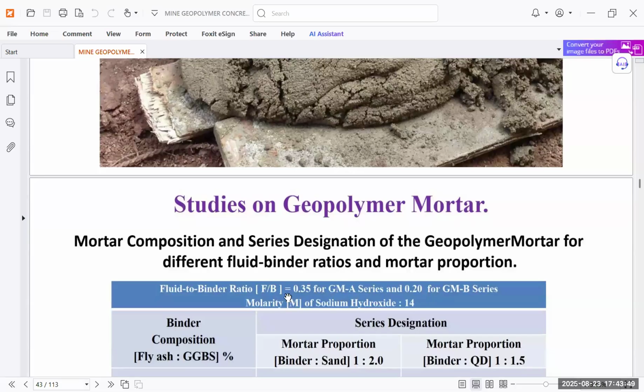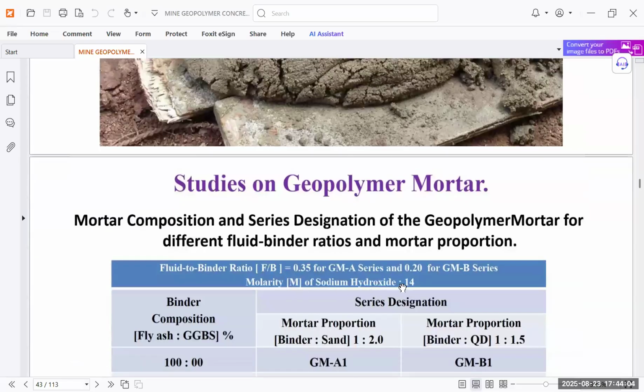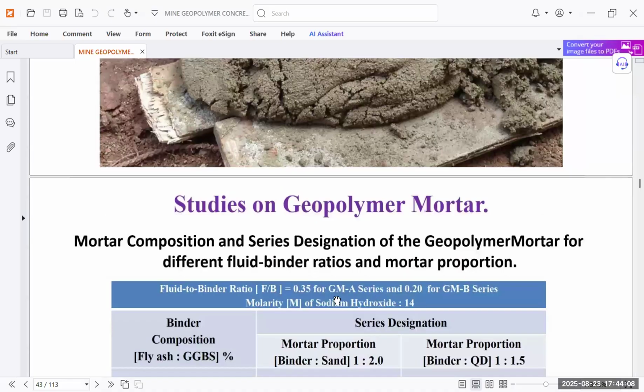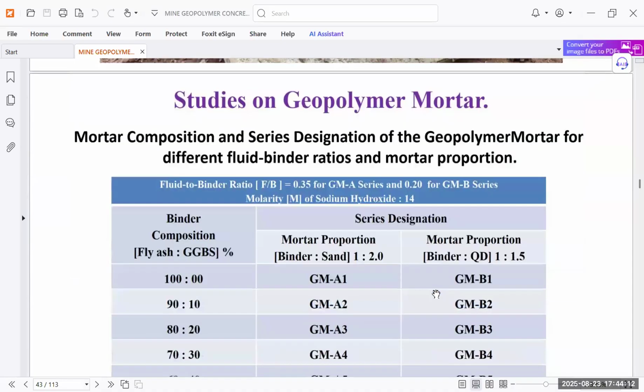This is 0.35 and this is 0.2 fluid to binder ratio. For the 0.35 fluid to binder ratio and the 0.2 fluid to binder ratio, this is called the GMA series and this is called the GMB series. The molarity of sodium hydroxide is taken as 14. For a fixed molarity, we can see that for different fluid to binder ratios, we have different results.